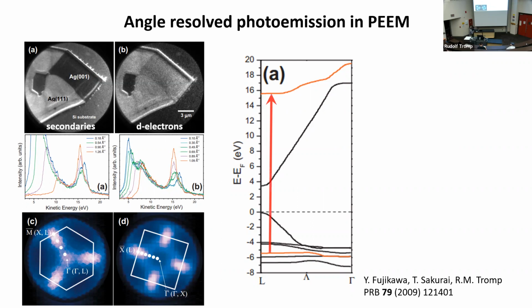So if we excite this, you see this is called the L point in the Brillouin zone. It's on the edge of the Brillouin zone. It turns out if we excite from this band here, which is an occupied band, up to this unoccupied state, that separation happens to be, by coincidence, exactly equal to the photon energy that we use, right? So we excite from this highly occupied state to this high density of unoccupied states, right? It's a resonant transition. So this is a very strong signal that we get here.